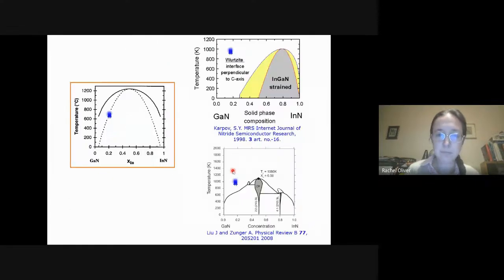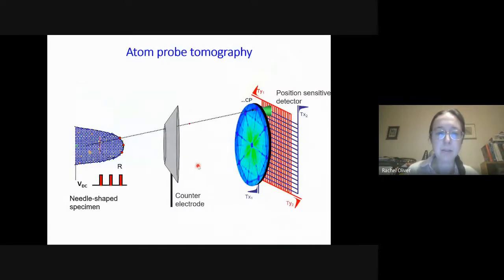Because of the presence of the counter electrode, the field will cause the atoms to fly off, I hope. Okay, this doesn't want to animate. The field will cause the atoms to fly off from the needle to this position-sensitive detector over here. And that will show us where the atoms land, which we can trace back via the radial symmetry of the field to where the atoms came from.